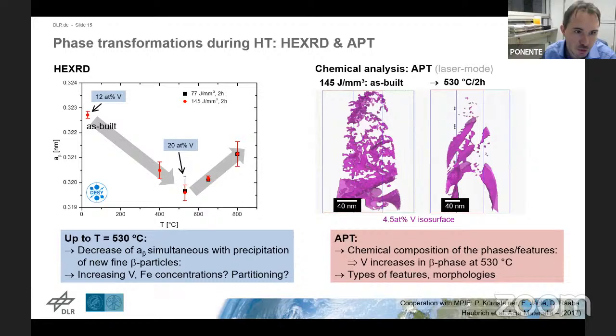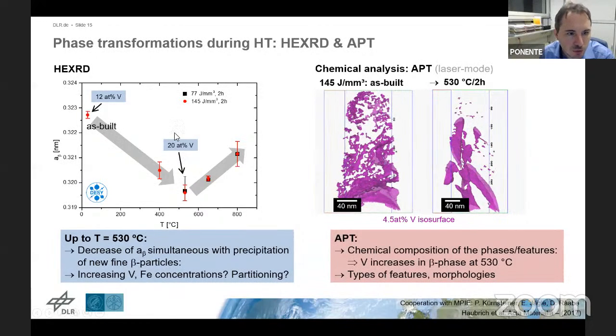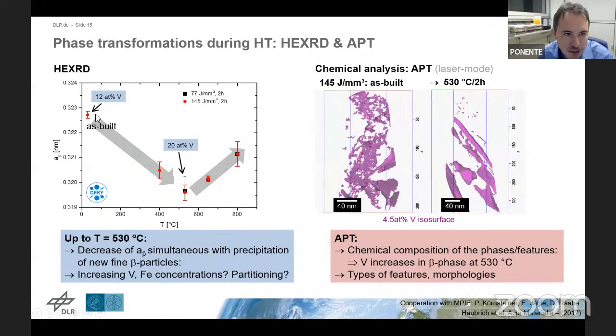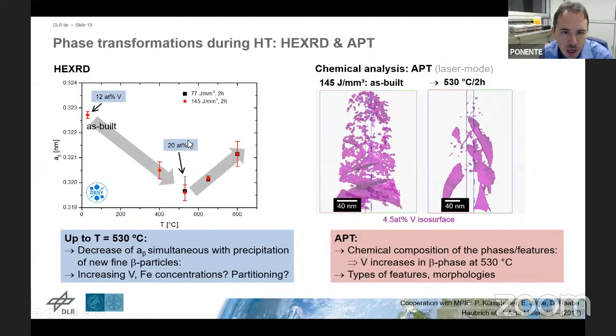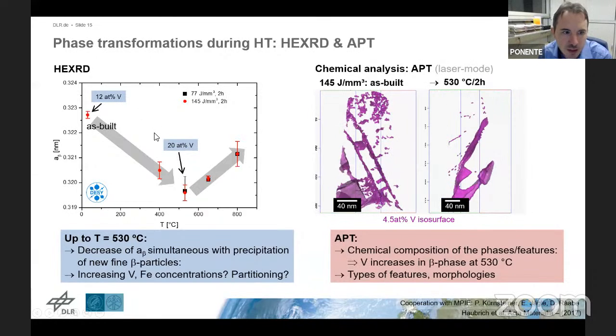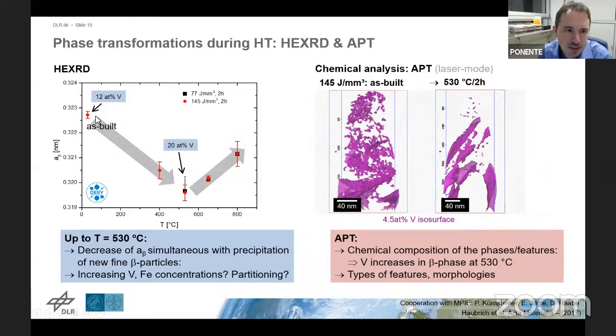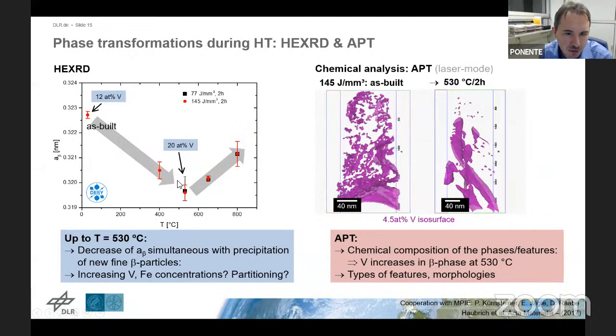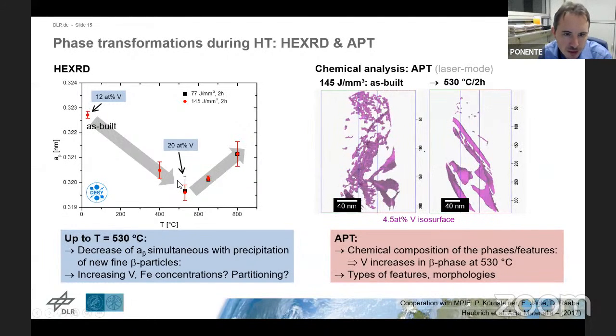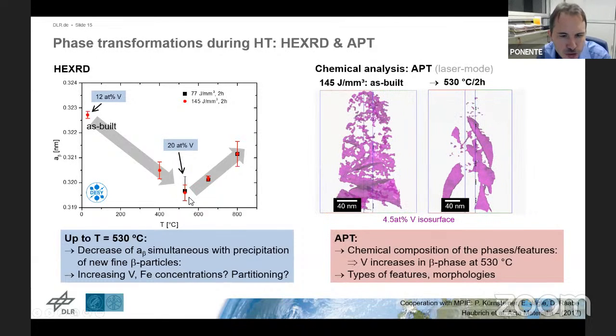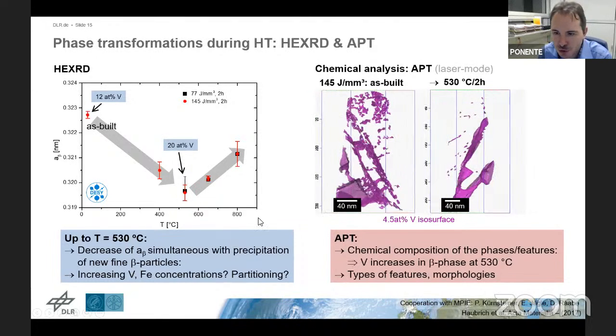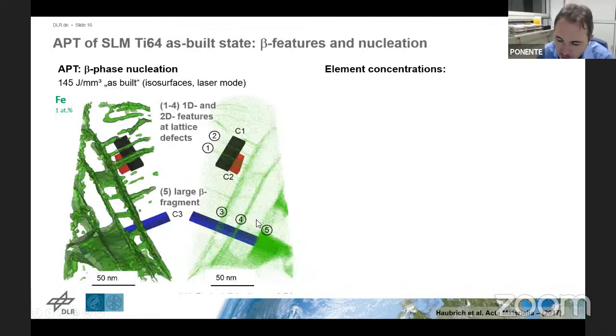And in fact, now on the left-hand side in the diagram, you see the composition of the beta phase in terms of vanadium that we get from the APT. And it confirms that in the as-built state, the beta phase is less enriched in vanadium than at 530. And this enrichment reduces again when going to higher temperatures. The APT is a very powerful technique and allowed us further insights in the formation of the beta phase during our treatments and the SLM.